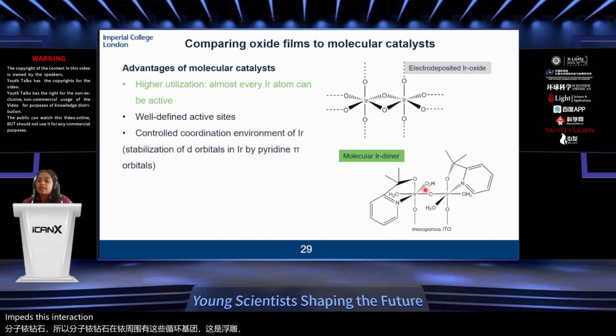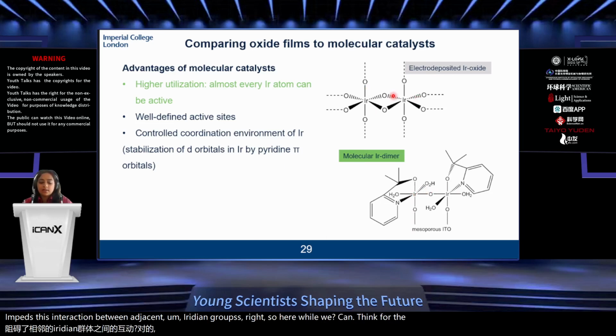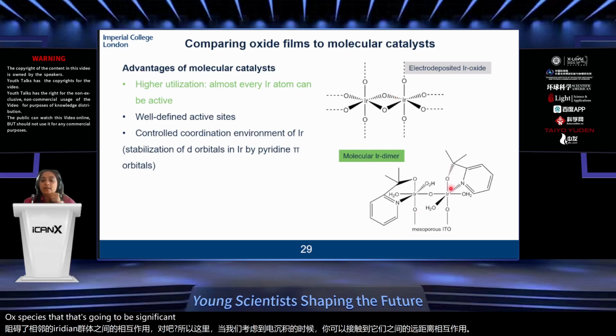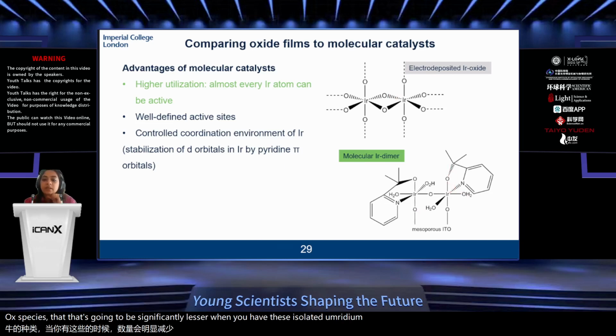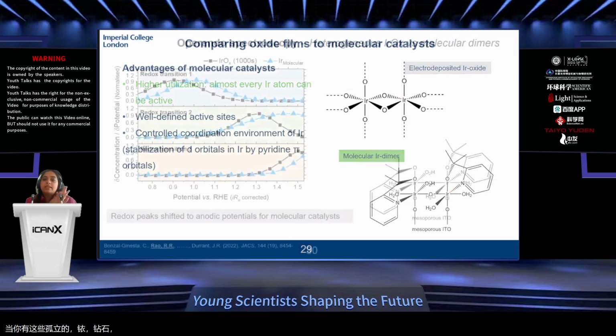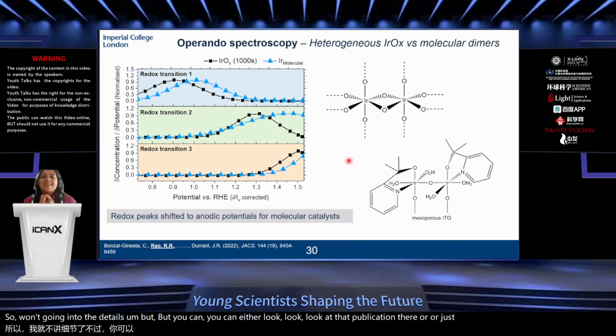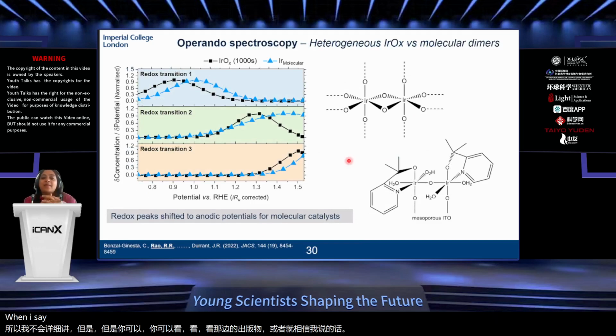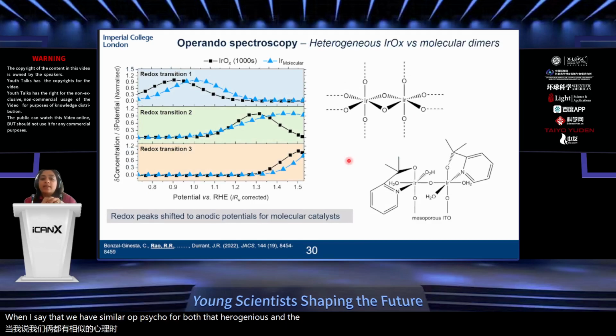interaction between adjacent iridium groups, right? So while for the electrodeposited oxide you can access these long-range interactions between these oxo species, that's going to be significantly lesser when you have these isolated iridium dimers. I won't go into the details, but you can either look at that publication there, or just trust me when I say that we have similar optical spectra for both the heterogeneous and the molecular catalyst, and